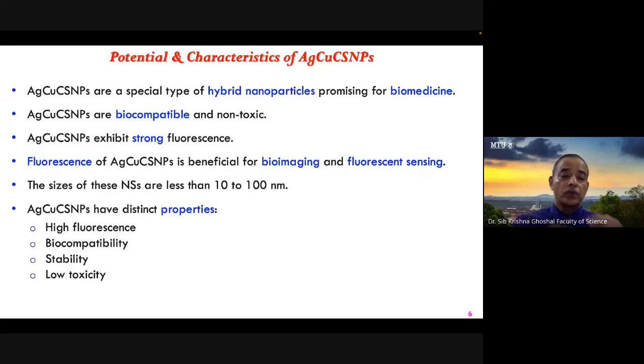And when this plasmon comes with fluorescence, the fluorescence property is the emission of pure color. This color can be controlled, and this radiation in the form of electromagnetic waves can be an enhancing factor for the creation of reactive oxygen species. That's the important part, that's the catch, that's the game. That plasmon and fluorescence together are responsible for a strong response. And this response can be useful for the creation of reactive oxygen species. And these reactive oxygen species will be responsible for the damage of the protein and the membrane in the bacteria and virus. And that is the way it will act as an antibacterial agent.